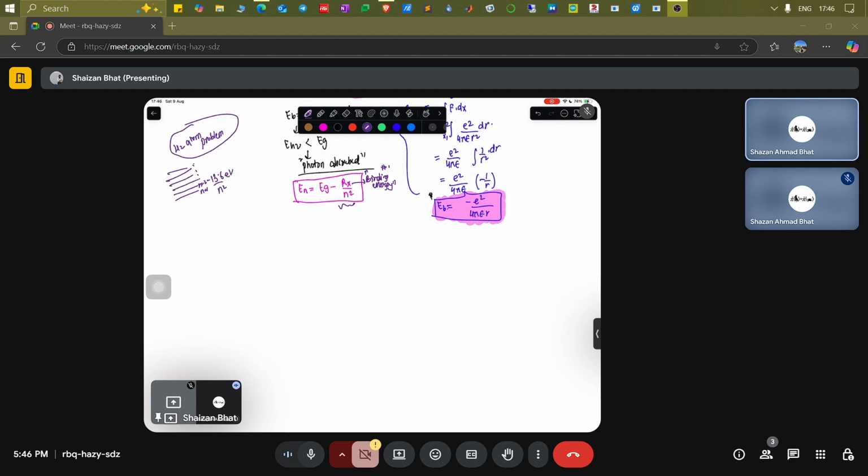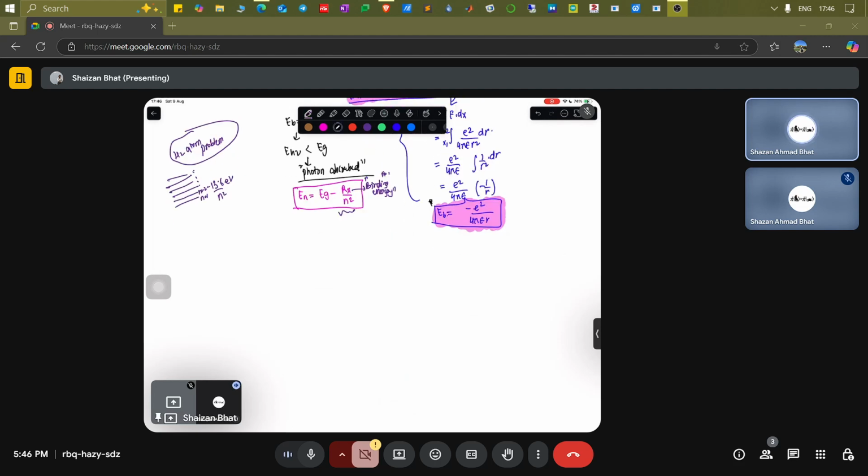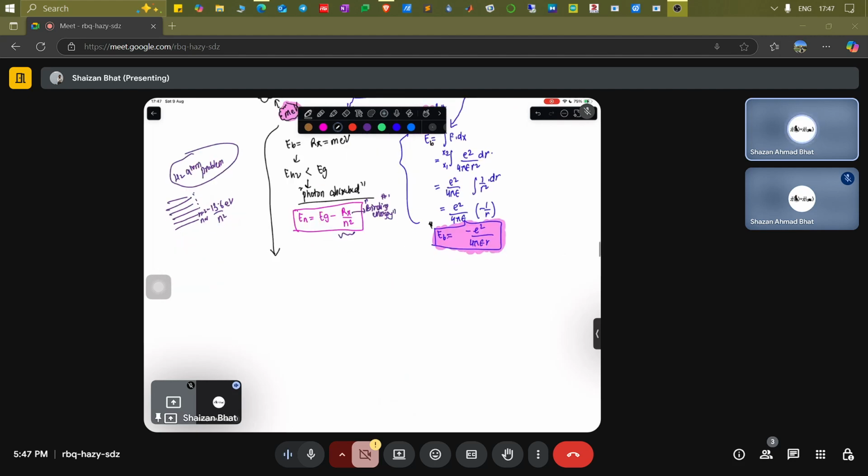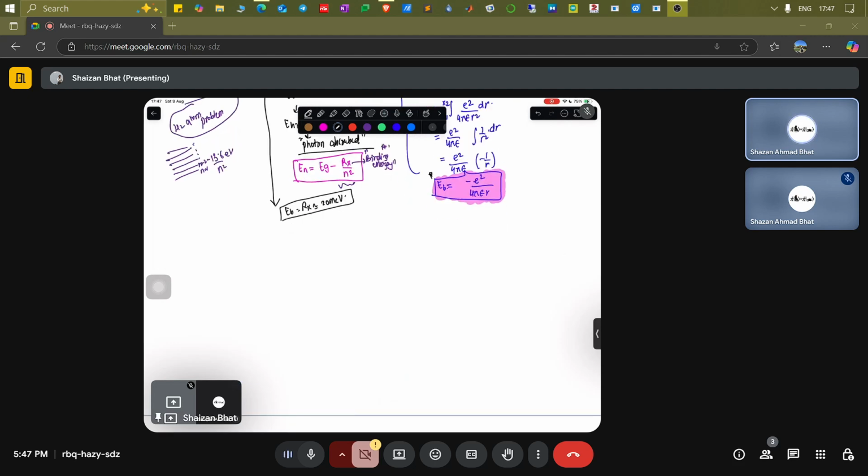Now these excitons can manifest as different peaks in the absorption spectra. They can also be extracted mostly at low temperatures, because the energies involved are on the order of milli electron volt. That's why it's mostly suitable to do low temperature measurements, so that you can get a glimpse of this change in the energy values. For example, if the exciton binding energy, or Rx, is on the order of, let's say, 20 milli electron volt, then you're not going to see it at room temperature.